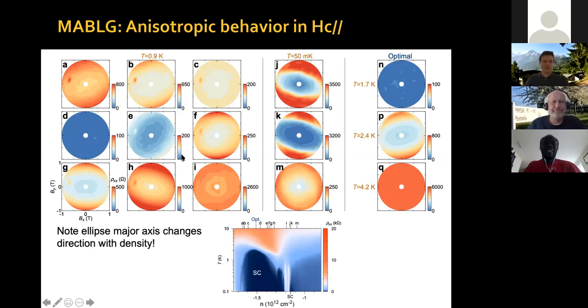And what you can see is that, for example, for E, the major axis of the ellipse is at about, I don't know, something like 45 degrees. Then you go to K or you go to H, and the ellipse has rotated, okay? The axis is minus 30 degrees or something like that. So this is very important because you might wonder, okay, we're measuring the anisotropic behavior of the critical parallel field, but maybe what happens is that your system has a very strong strain, and the strain is what is selecting a particular direction, okay?